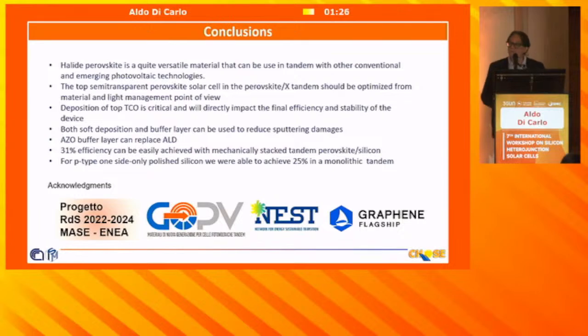So I can conclude now. I showed you that it's possible to use simple ways to create tandems. I showed the mechanical stacking, but also the use of AZO nanoparticles to avoid the use of ALD. And also with mechanical stacking, you can get more than 30% in a simple laboratory-scale system. Thanks a lot.